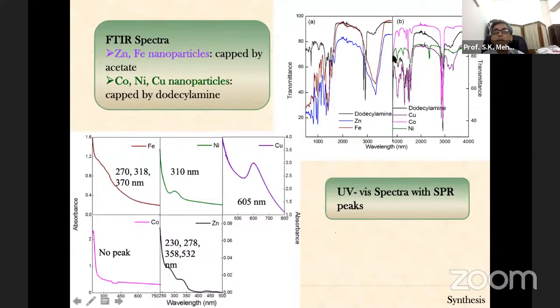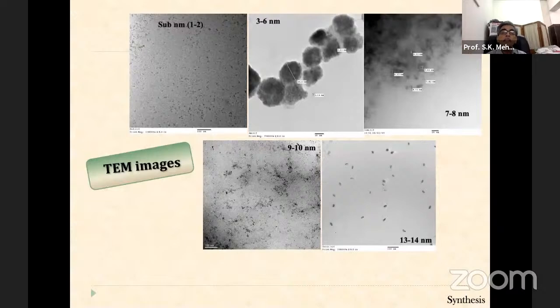IR will tell you which components are coating the nanoparticles, and you can also see pure dodecylamine, which we have used, and where we have zinc introduced, where we have iron introduced, and you can differentiate. Similarly, you have dodecylamine with copper, cobalt, nickel. So these are initial techniques which can be done. Particle size measurements can be done. Some you can see have very small particle size, 1 to 2 nanometers, and it goes to 13 to 14 nanometer nanoparticles. Again, this can be easily done.